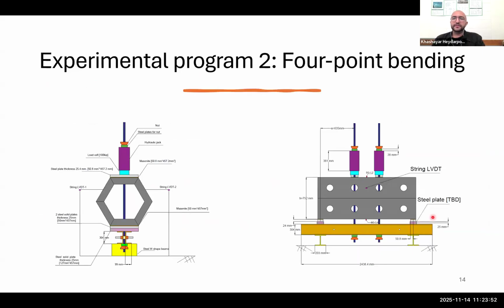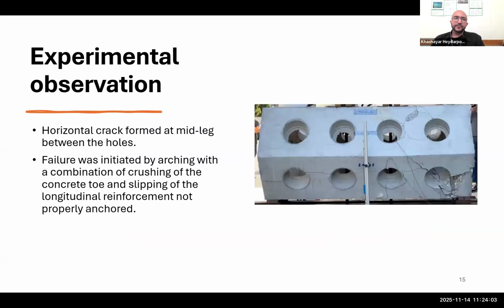And the other 2 specimens were tested under 4-point bending. And you can also see the schematic view of the test setup. And it was also observed from these experiments that the horizontal cracks formed at the mid-leg between the holes, and failure was initiated by arching with a combination of crushing of the concrete toe and the slippage of the longitudinal reinforcement that was not properly anchored.